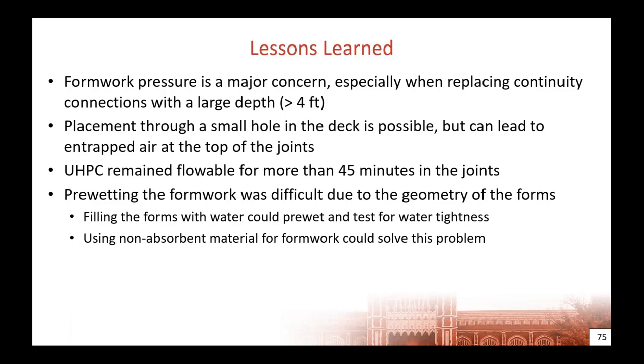And I think part of this might have just been because it was such a small hole. Another way that you might be able to fix this is to provide some sort of weep hole somewhere else to allow air to come out. That might help remove the air a little more efficiently, so you won't have to come back and top off the material. And as we mentioned, the flowability is very nice for placement, but it can cause problems later on with your formwork, and the fact that it will continue to move when you think you're finished.